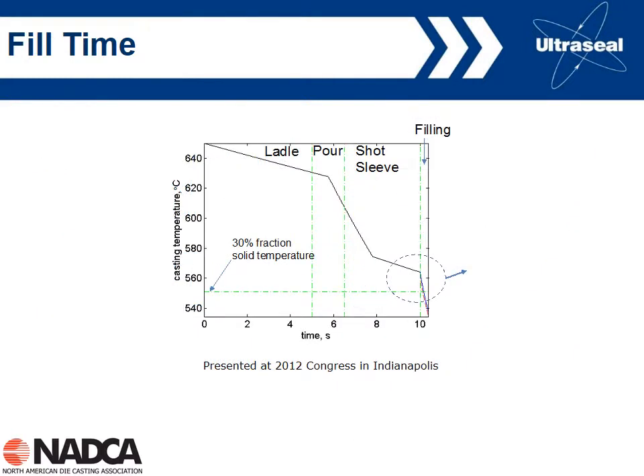And here's another thought about fill time. This is more recent work that was actually presented at last year's Congress, 2012 in Indianapolis. Basically, it's addressing the fact that we don't really know the temperature that we're filling our die with. Here we're looking at the entire process of getting the metal from the furnace on the left all the way into the die, so through the ladle, through pouring, into the shot sleeve, and then actually filling the die. And the actual die filling time, as we can see here, is a very small percentage of the entire process, maybe as little as 1% of a much longer process. So if we want to control the entire process, we have to look at how the metal gets into the shot sleeve, not just how fast we're filling the die.